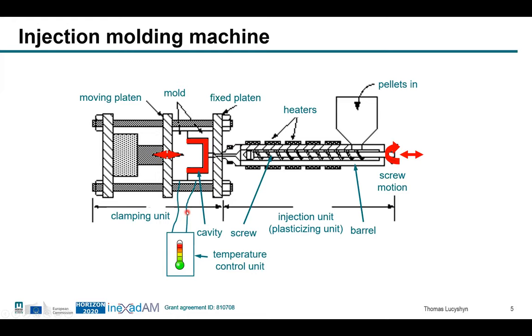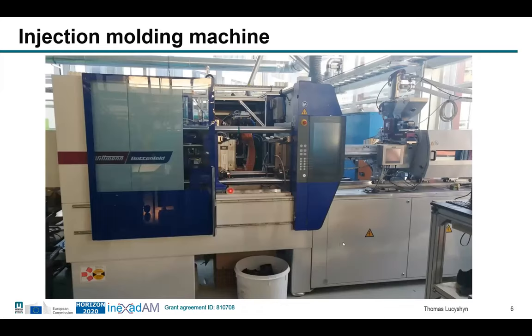So it needs to be a compromise between cold enough to be fast in processing, to not lose time, to be economically efficient, but not too cold so that maybe the melt freezes too early or the surface quality is bad. So we always need to find a compromise between sufficiently high for a good quality, but sufficiently low for a fast and economically feasible process. So that's how a real machine looks like. It's one of our machines in our lab, one fully electric machine. Here on the right-hand side, we see the injection unit.